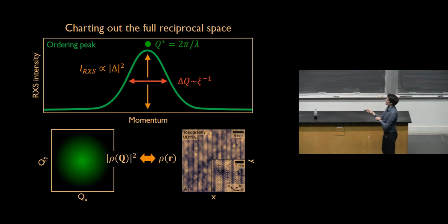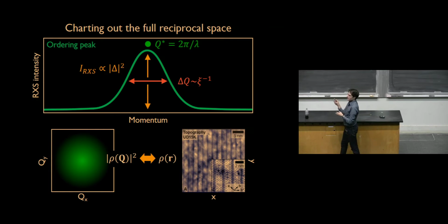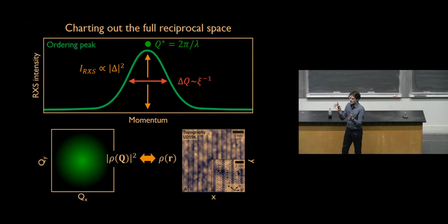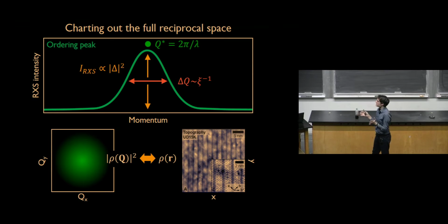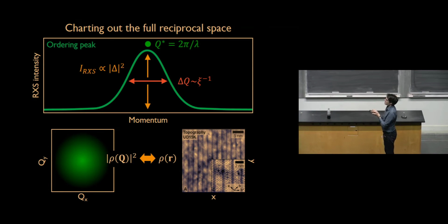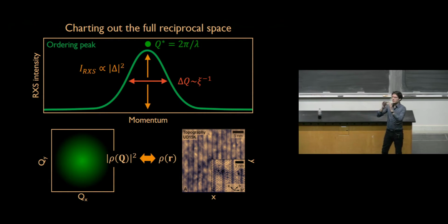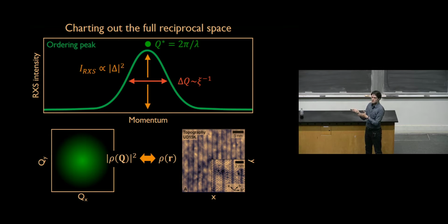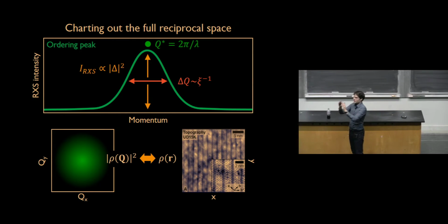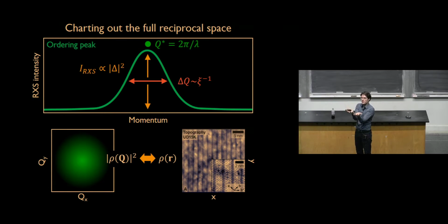So yes, absolutely. And we thought about this because we realized at some point that when we measure these features in reciprocal space by slicing across the peak, then we lose a lot of information. These peaks are not defined in one-dimensional momentum space. The momentum space is three-dimensional because our material is three-dimensional, right? So these peaks are really kind of spheroids or ellipsoids in reciprocal space, and we're only slicing along one direction, and we're only taking very, very little information out of the full information that's available in reciprocal space.